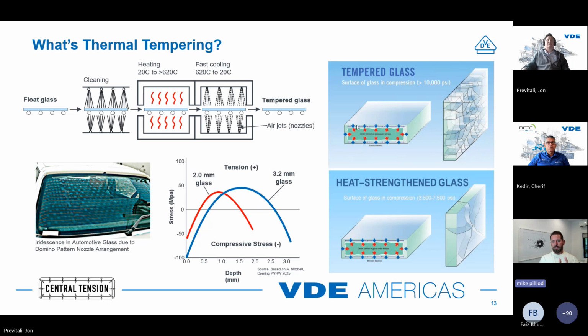At 2 millimeters, it's not impossible to fully temper glass, but it gets much more difficult because you don't have enough thermal mass in your glass to cool down the surfaces and allow the inside meat of the glass to continue to shrink to get your surfaces into compression.